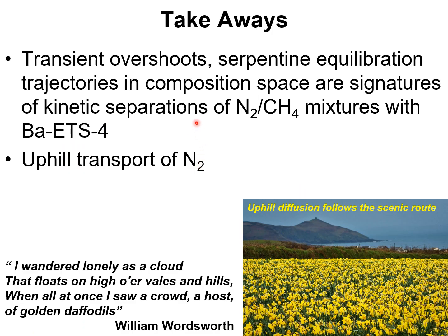The takeaways from this presentation are summarized in the slide. Transient overshoots and serpentine equilibration trajectories in composition space are signatures of kinetic separations of nitrogen-methane mixtures using barium ETS4. Our simulations have established the occurrence of uphill transport of nitrogen within the pores of barium ETS4.